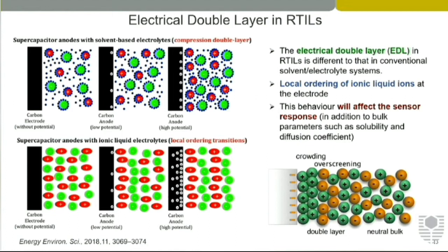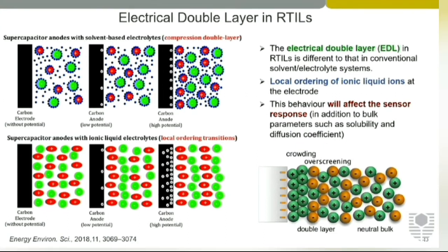There are different cases where you can have what's called crowding and over-screening. So in this case, over-screening could mean that you might have two layers of cations to balance the charge at the electrode. But what's really, really important here is that the structure here is much more dense than the structure in the bulk. And so if you think we've got to get our analyte gas coming through the bulk, but also to the electrode surface, does the diffusion coefficient or the solubility of that gas change in the double layer compared to in the bulk?